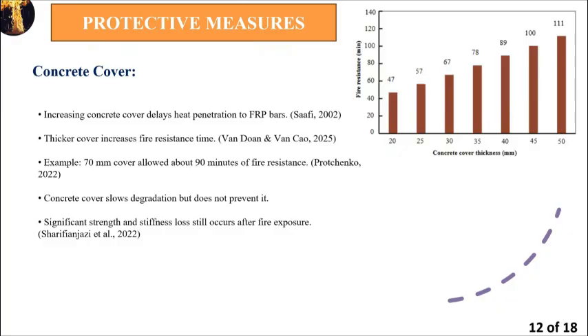Research also shows that increasing the concrete cover can significantly improve the fire resistance time. For example, a concrete cover of just 70 millimeters can allow a beam to resist fire for up to 90 minutes, which is very important. However, it is also important to understand that the concrete cover does not completely prevent damage. It only delays the heating process. So if the fire lasts long enough, the temperature will still reach the FRP reinforcement and degradation will occur.